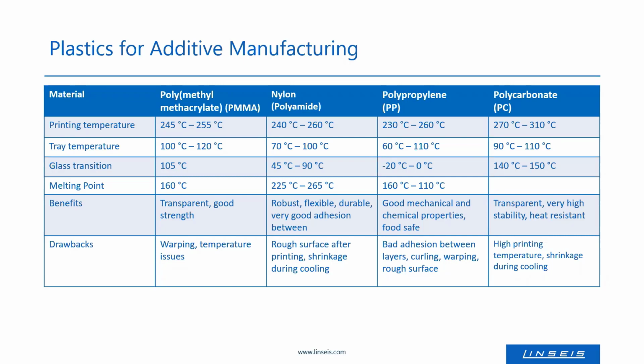Nylon, for example, is also robust, flexible, really durable, and has a very good adhesion between the layers. The problem here is that it has a really rough surface after the printing, but this can be polished afterwards. So here a further processing step is needed. Additionally, the material shrinks very much, or more than the other materials, during the cooling process. So this needs to be considered as well when printing an object.